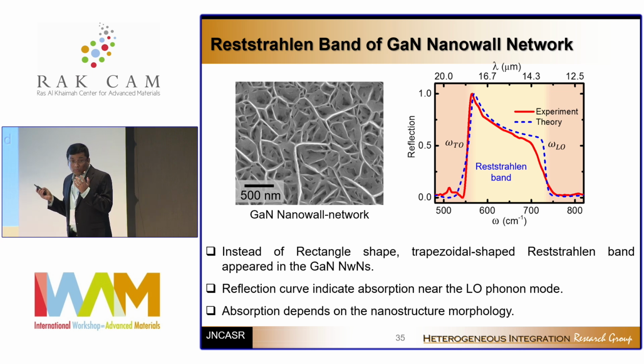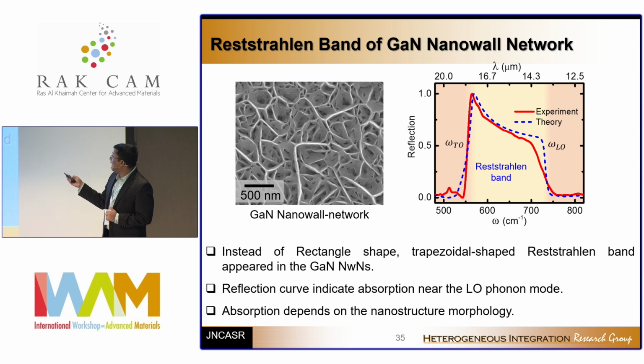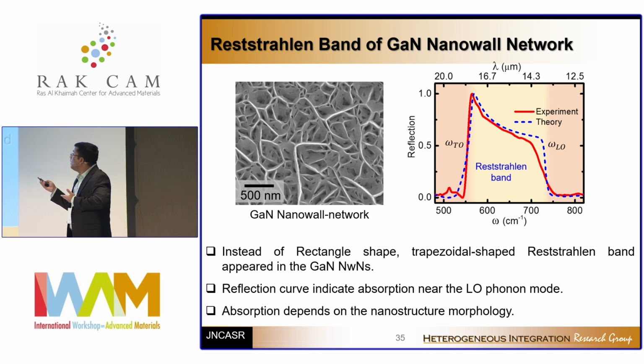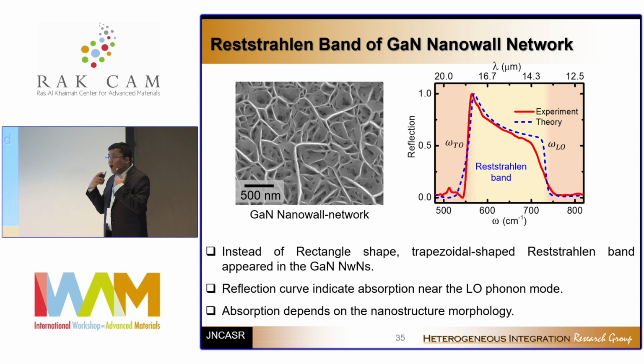Now, what does it mean? Well, it means that close to the LO phonon frequency, the reflection has gone down. That means absorption has gone up. Because the transmission is 0, we have a backside metallic plate. So if the absorption has gone up, what is that absorption and how is it impacting these optical properties? That is what we figured out in this case.